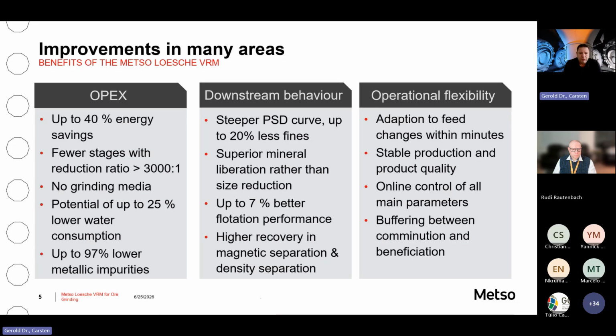Other points that we will touch on are the downstream behavior, like the steeper particle size distribution curves we get, with up to 20% less fines, minus 20 micron. We see superior mineral liberation rather than just size reduction. And like already stated, up to 7% better flotation performance. The particle size distribution out of the machine, because it's pretty steep, also improves the recovery in magnetic separation or density separation.